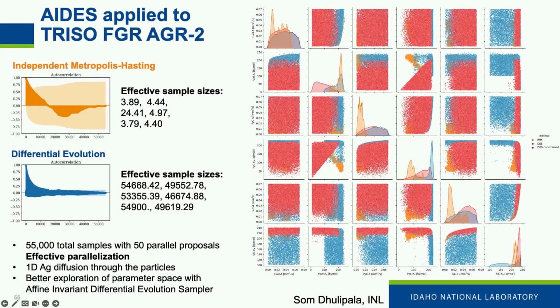So anyway, what we're currently working on is adding constraints, and we can do that very easily. In this case, we're just putting in two constraints. We're saying that one activation energy is larger than the previous energy, is larger than the previous energy, and that forces a certain amount of ordering. And then we can see that at least here in this last layer, our distribution, which was this blue one, the yellow one is crap, the blue one was very wide, and now the red one with the constraints is suddenly quite a bit peaked. So we think we need to add a little more physics to that.